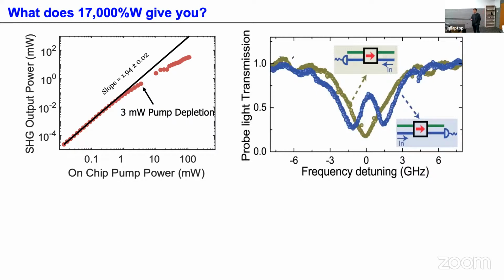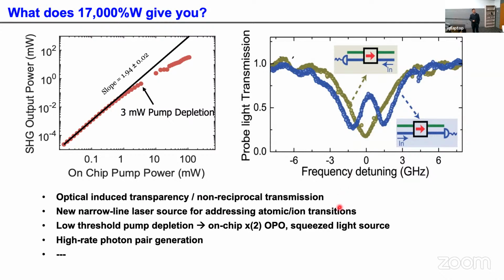You can measure that super mode by looking at the transmission through the device under a strong pump condition. You can see the splitting of the mode. This only happens in the phase matching direction. If you go backward, there's no phase matching, and you see a regular transmission dip. So you can see that contrast, which looks like electromagnetically induced transparency. It's just very strong coupling between the micro and optical modes, and a lot of people develop optical isolators based on a similar principle. With that mode splitting, you can estimate your single photon coupling rate of this 1F 2F coupling. And there are a lot of new things you can study here, including frequency conversion.